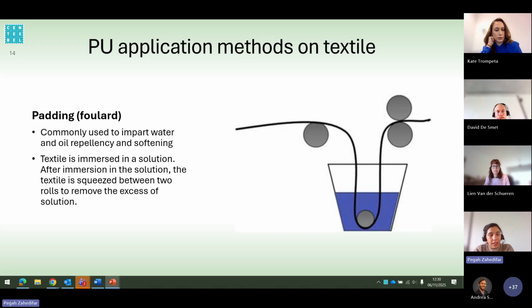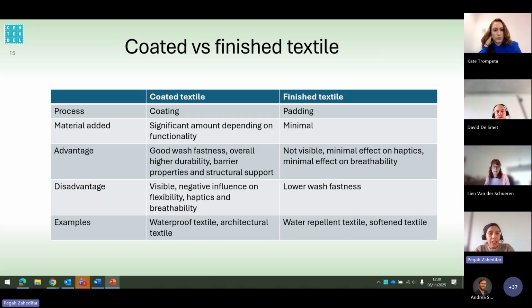The other alternative is padding, in which we apply a treatment on the textile at the fiber scale, and this is the way that we dip or immerse the textile in a bath that contains the polyurethane, and then we drag the textile and squeeze it between two rollers in order to get rid of the excess amount of the polyurethane, and then we have the drying and curing steps. Each of these methods has its own properties, advantages and disadvantages.